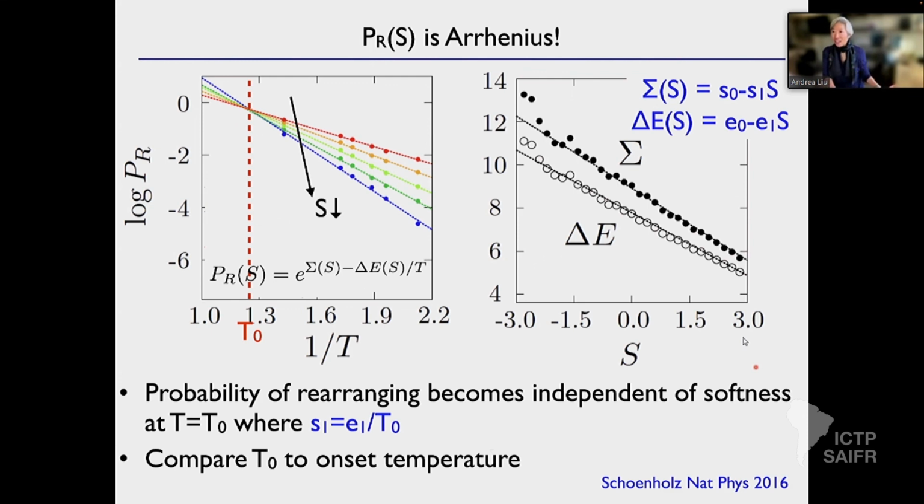Systems with low average softness are more brittle, as I was just saying. So can we design solids to have large average softness? And what are you designing? It's usually the preparation protocol. So you have a cost function, which basically maximizes softness, and the preparation protocol is characterized by a number of variables, and then you figure out what it takes.